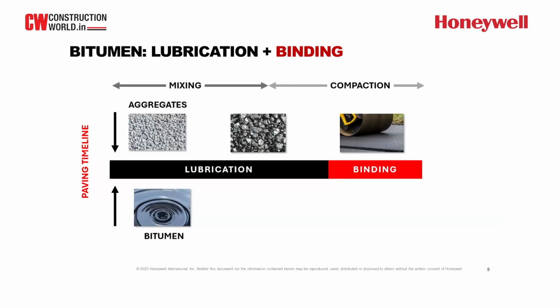And then you have a compactor come in to compact the asphalt mix to a certain thickness, certain density, or certain air voids. So you can say for most of the process, the production process, the transportation process, and the majority of the compaction process, bitumen behaves like a lubricant, right? The bitumen coats the surface of the aggregate to make the flow and the moving of the aggregate easier. They don't stick together, and it also reduces the friction. So even during the compaction, we want to have low friction among the aggregate, so when you compact, they can move around each other easily. It'd be easier to achieve the density or the air voids.